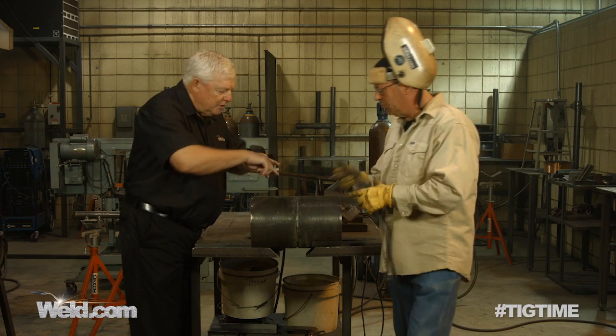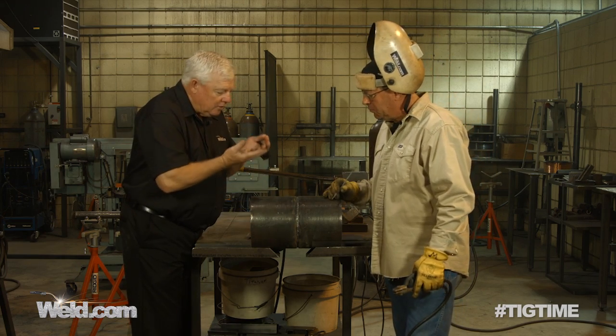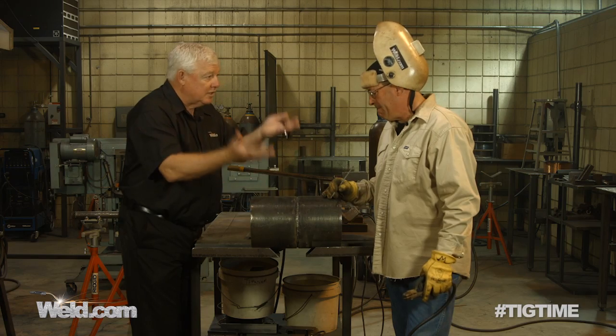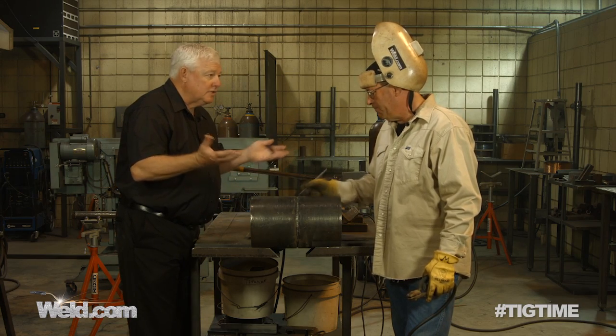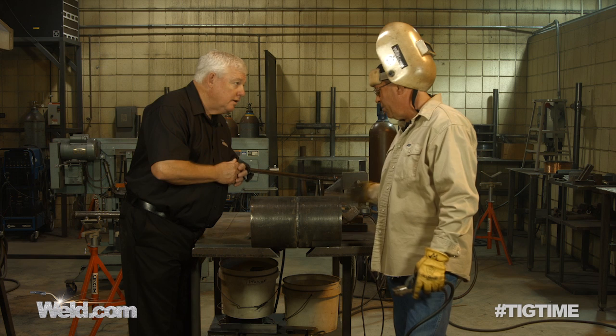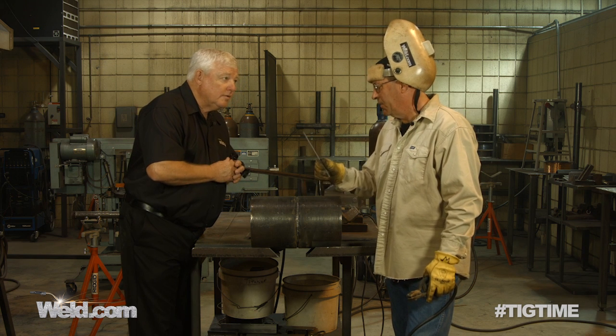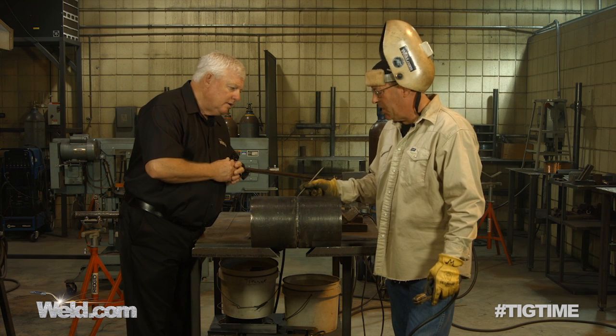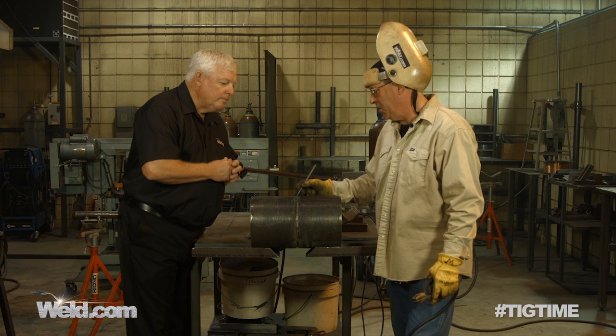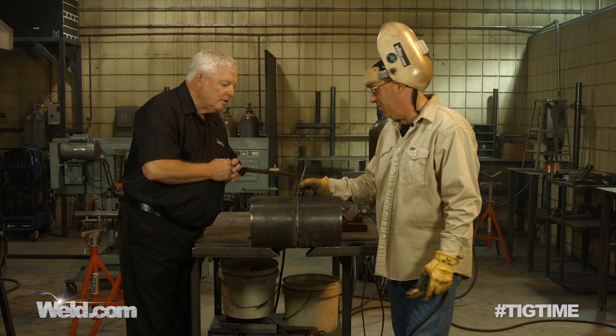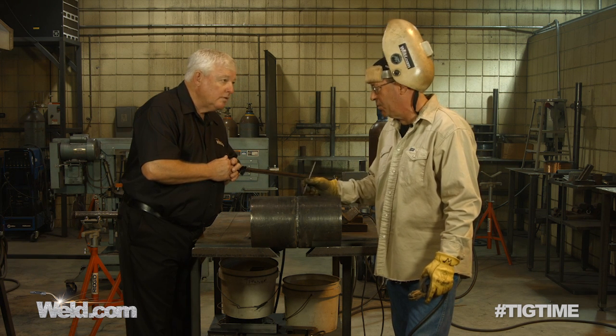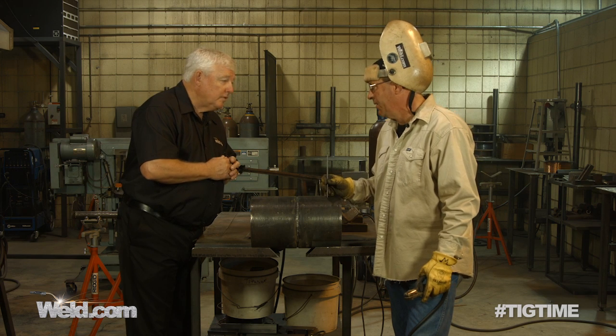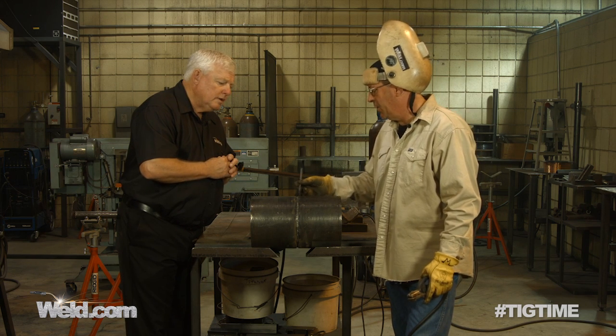Okay, Bob, I see you put your second pass in, and it looks like it wetted out a lot nicer. It's now getting cleaner as it seems to come up. What's the next step? Okay, the next step, I've turned my amperage back down to about 80 amps. I'm a little bit in between here. I do like to run the 5/32, but I'm going to go ahead for demonstration purposes and run this with 1/8th. So I want to slow down a little bit.